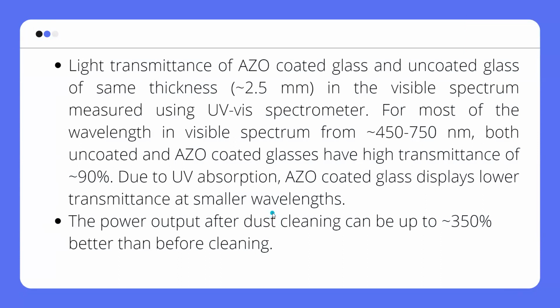The conclusion of my work is: the transmittance of AZO-coated glass and uncoated glass of the same thickness in the visible spectrum was measured using a UV spectrometer. For most wavelengths in the visible spectrum, from 450 until 750 nanometers, both uncoated and AZO-coated glasses have a high transmission of 90%. Due to UV absorption, AZO-coated glass displays low transmittance at smaller wavelengths.